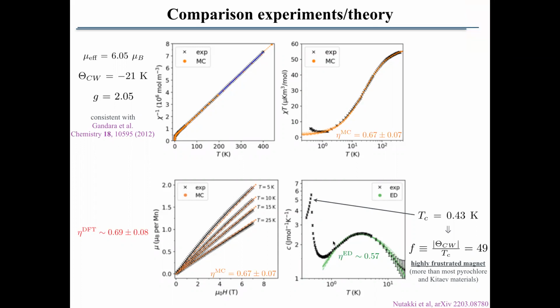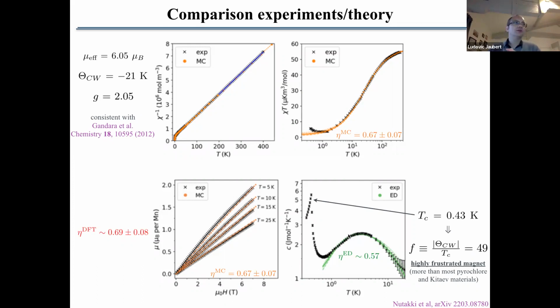Well, why would you expect quantum fluctuation to be at such a large temperature when you have a classical spin? I mean, 5.5. It's just because the continuous classical spins cannot reproduce the specific heat properly, because the classical fluctuations being continuous, you cannot reproduce the entropy, and so you cannot reproduce the specific heat. So if you want to compare things below this bump, you need to include the discreteness of quantum mechanics. So it's in that sense that the quantum mechanics kicks in.